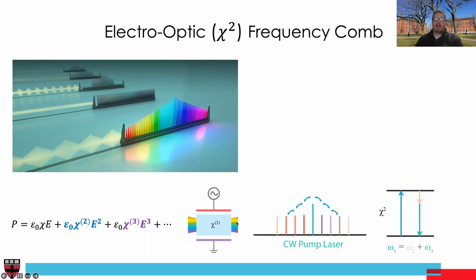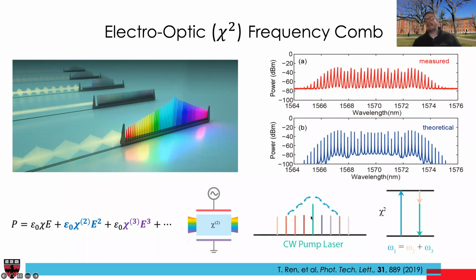The lower the V pi of the modulator, the more comb lines you can get. And indeed, that has been done with conventional lithium niobate modulators, of course. And in this work referenced here, we have demonstrated this with thin film lithium niobate as well. The advantage of our approach was that V pi was low, and therefore we could generate more comb lines than what you can typically do in a conventional device.